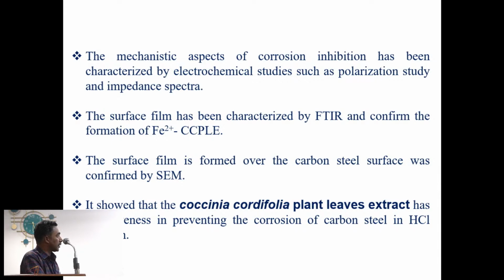The mechanistic aspects of corrosion inhibition have been characterized by electrochemical studies such as polarization study and impedance spectra. The surface film has been characterized by FTIR and confirmed the formation of Fe2+. The surface film formed over the carbon steel surface was confirmed by SEM. It shows that the Coccinia cordifolia plant leaves extract is effective in preventing the corrosion of carbon steel in hydrochloric acid solution. Coccinia, English name ivy gourd or scarlet gourd, sir. Common name is.